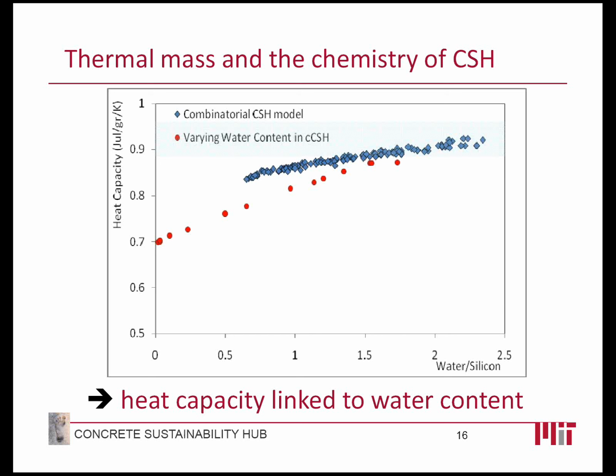So the idea is the following: as we move towards large values of the calcium over silicon ratio, in fact, we have less silica in the structure. In fact, this is a way to accommodate more water molecules. So there is a linear relation between the water content and the calcium over silicon ratio. Now, turning to the heat capacity as a function of water, this is why we also have this linear plot in this case. The blue points are for exploring all the possible chemistries of CSH, as a function of calcium over silicon ratio and different water content. And the red points are taking the most common calcium over silicon ratio, which is 1.7, which also has 1.7 for the water to silicon ratio.